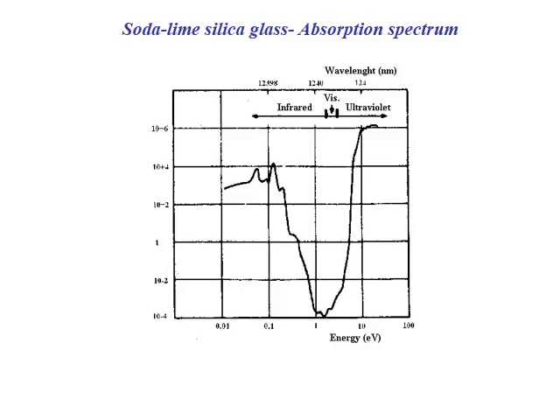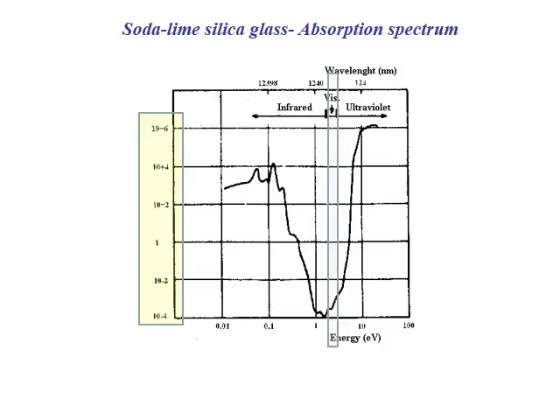This figure shows a typical absorption spectrum of a silicate-based glass. It shows the absorption coefficient as a function of the energy and wavelength. In fact, all dielectric materials will display a spectrum with this V shape. The first thing to note is the huge variation of the absorption coefficient, 10 orders of magnitude. You also see that the visible range is a small range of the x-axis. The spectrum runs from the UV to the infrared.